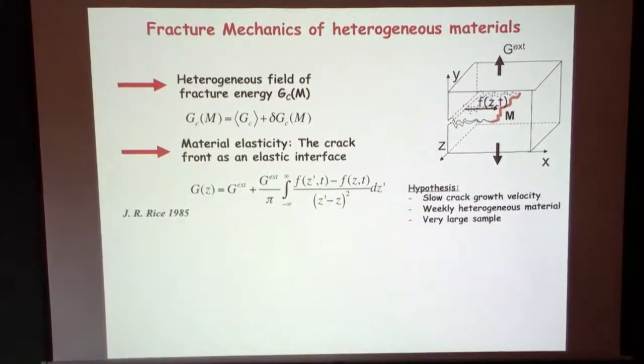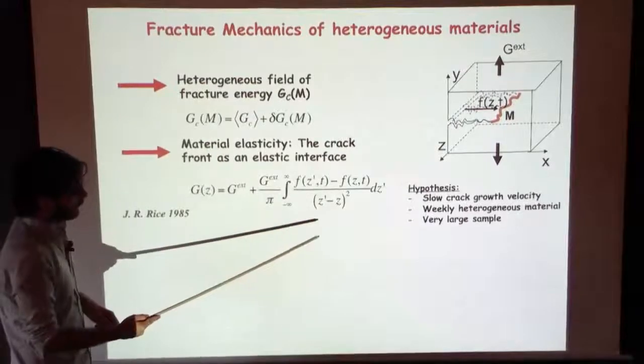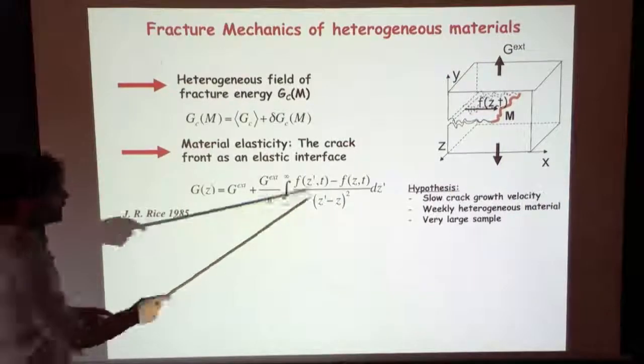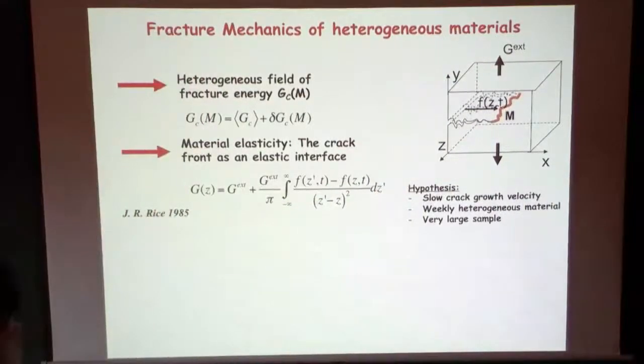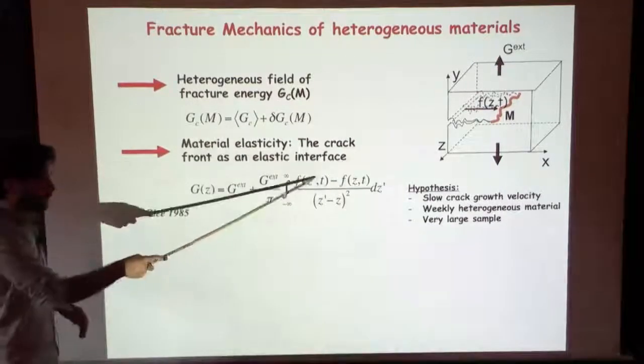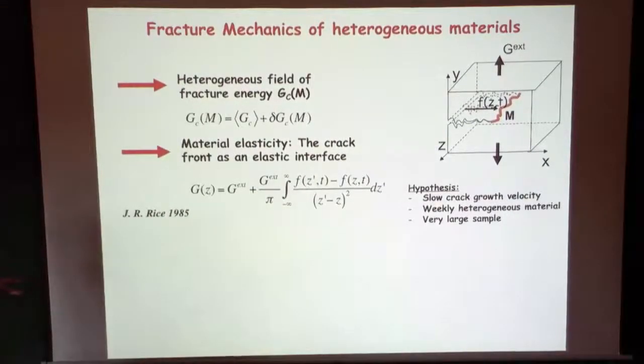And this non-local term, one more comment, arises from the fact that if you have a perturbation here, but maybe we see it better on the next slide. If you have a perturbation here, it perturbs the stress field in a whole area around the perturbation, so you have an effect on the long range. So basically, my understanding is that the integral part is really the line tension part. Yeah. You try to stretch it flat, right? That's it. It's a specific kind of line tension: if you have a sinusoidal perturbation of the front, the restoring force goes as 1 over the wavelength, while if you had a local, classical line tension, you would have 1 over the wavelength squared.